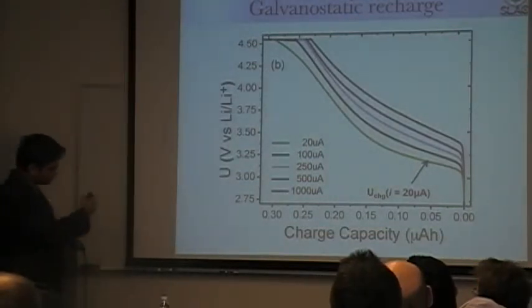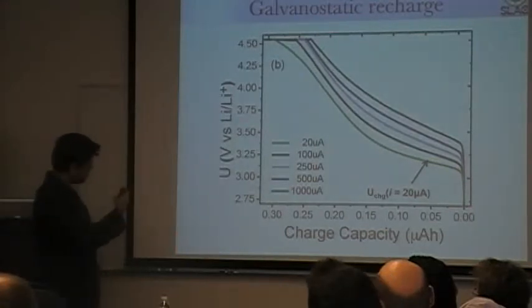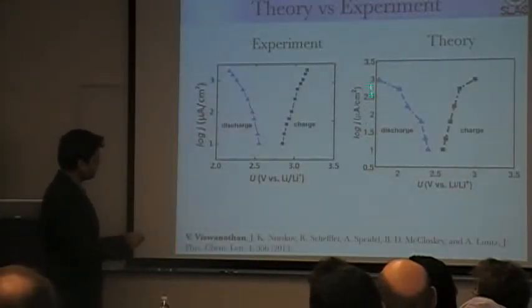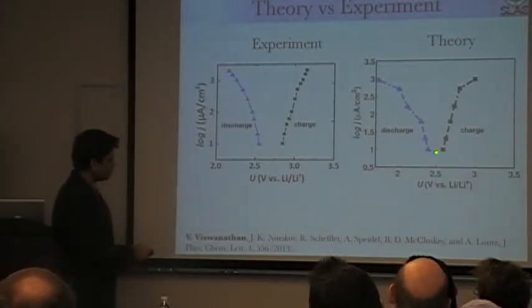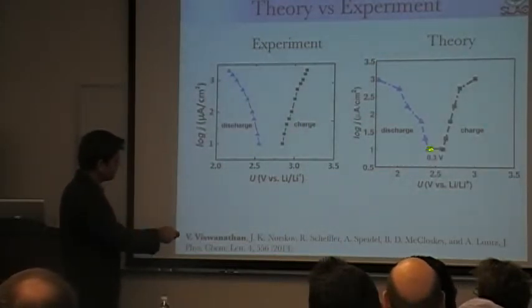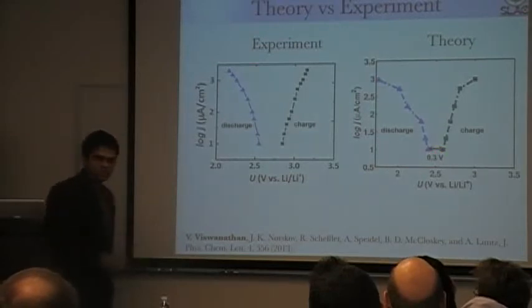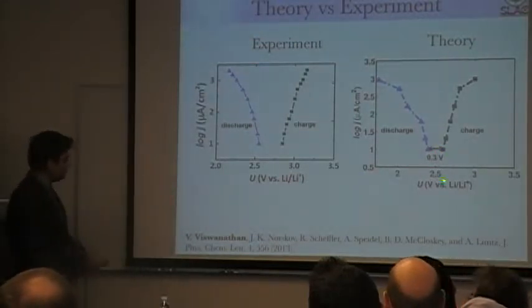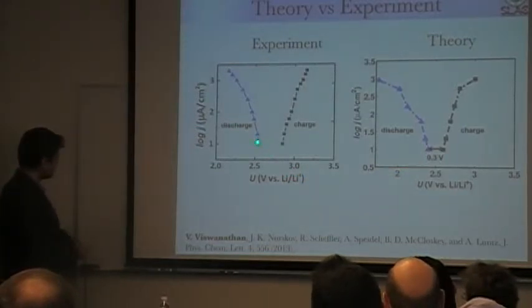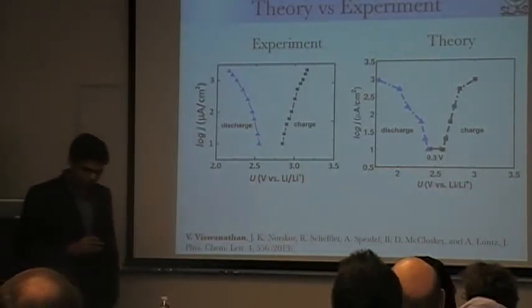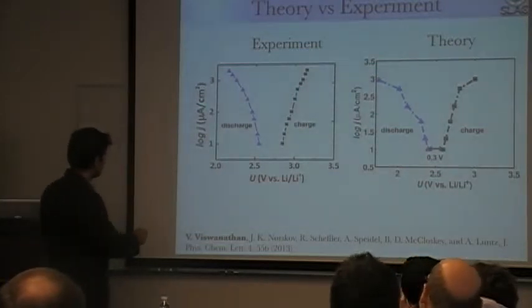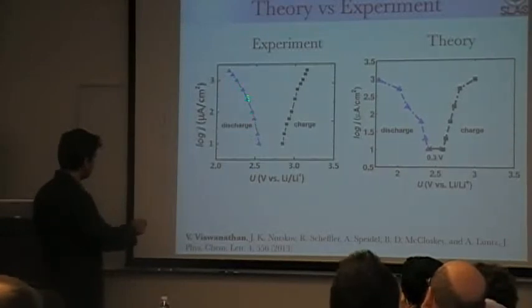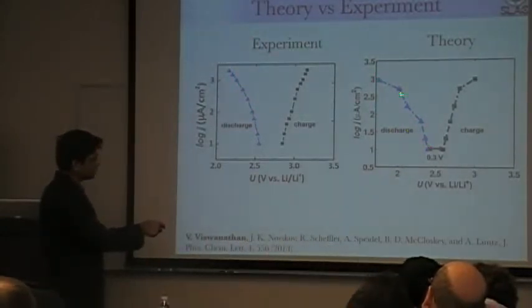We can carry out a more concrete analysis of the voltage dependence of the current in a Tafel plot, showing log of current as a function of potential. Theory and experiment are compared. The most important question is the distance between the two curves — that is the voltage penalty. We predict about 0.3 volts and experiments show about 0.4 volts, which is excellent semi-quantitative agreement. We even capture some finer features: the non-linearity in the discharge curve arises because discharging on a terrace costs a high overpotential.